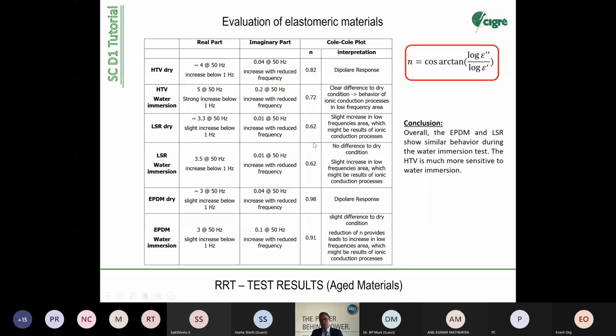So the conclusion here is overall the EPDM and LSR show similar behavior during the water immersion. The HTV is much more sensitive to water immersion.